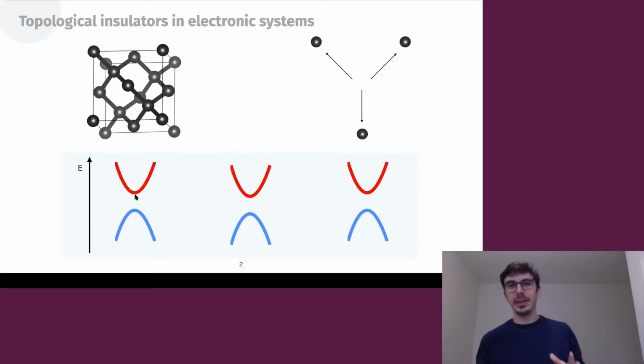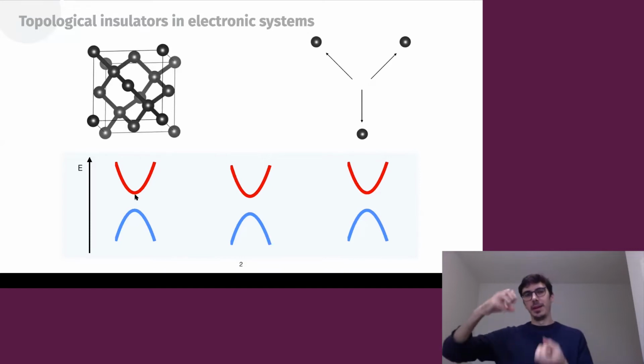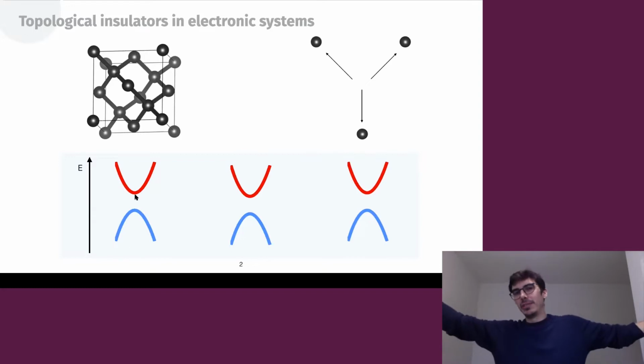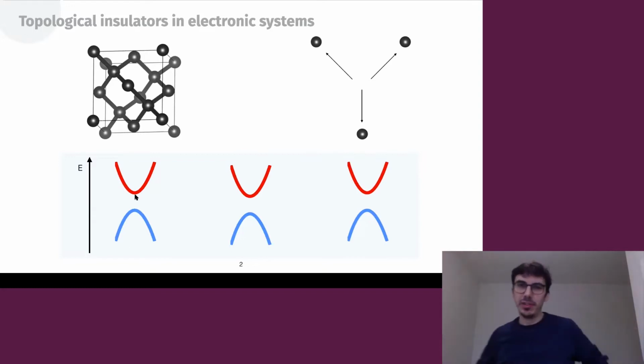And then what we can do in diamond, you can imagine that you pick the carbon atoms that make up diamond and you pull them apart, as shown on the right of the diagram, all the way to the edges of the universe. So every carbon atom at one edge of the universe. And this is what we call the atomic limit. And in the atomic limit, the system is also insulating. The electrons cannot travel through different carbon atoms.